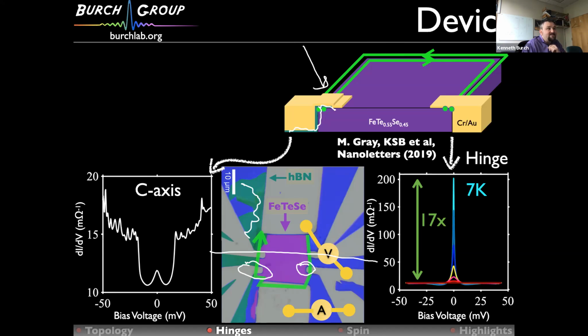Sorry. So Ken, sorry, naive question. Is this all done in a normal phase above TC? No, this is all below TC. So what you see, the dark red line on the right-hand side is the normal state. And then as you see the zero bias peak emerging, as it goes from red to blue, it's when we're cooling below TC. So we never see this in the normal state. And the C-axis data is just at the lowest measured temperature. It's equivalent to the blue line on the right-hand side.